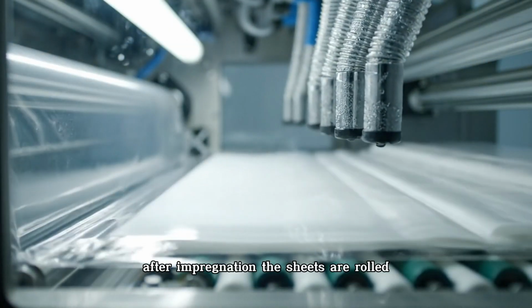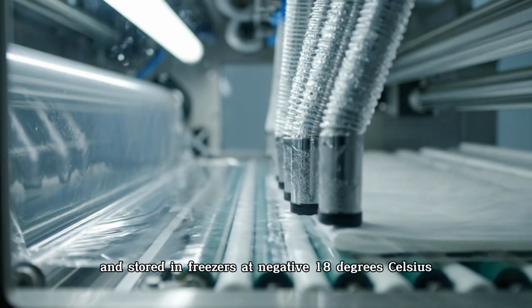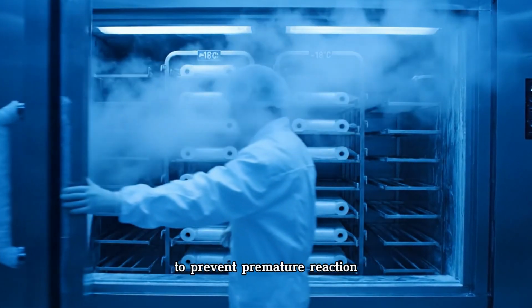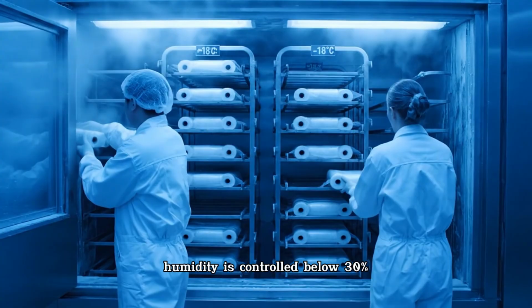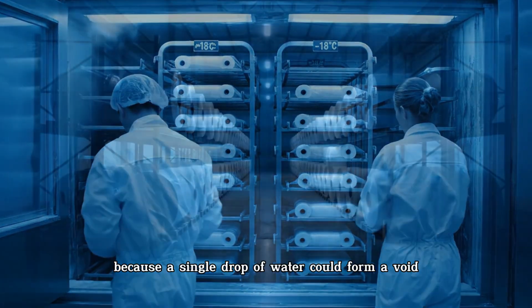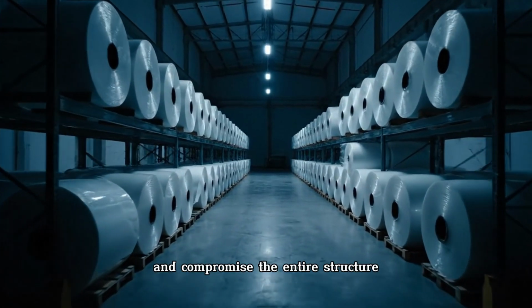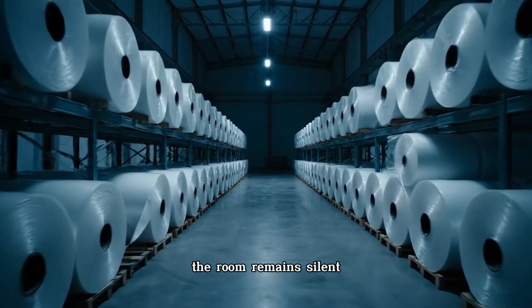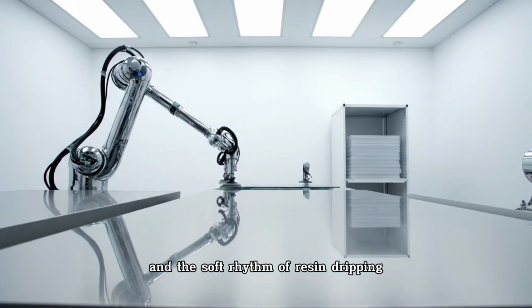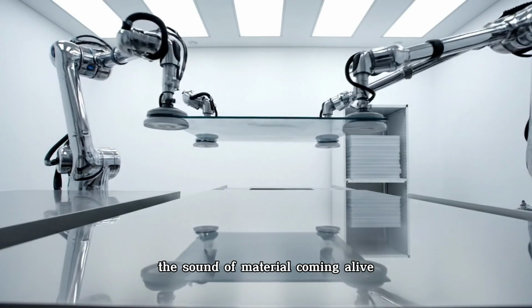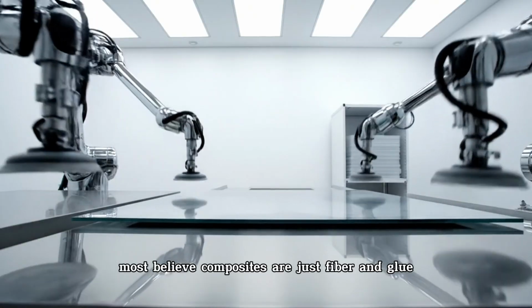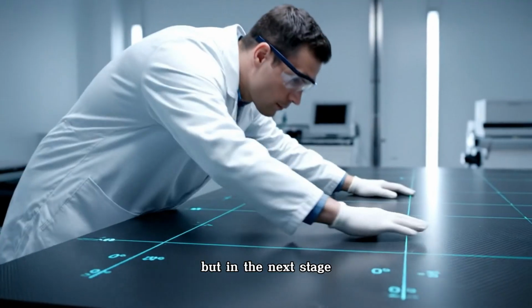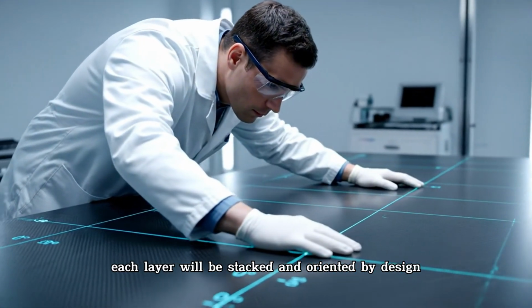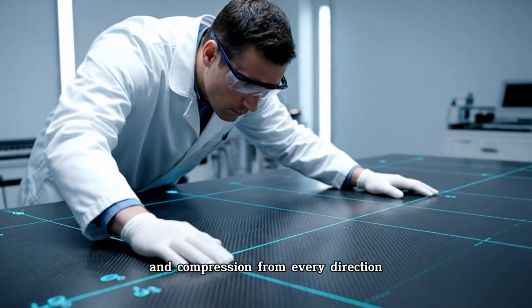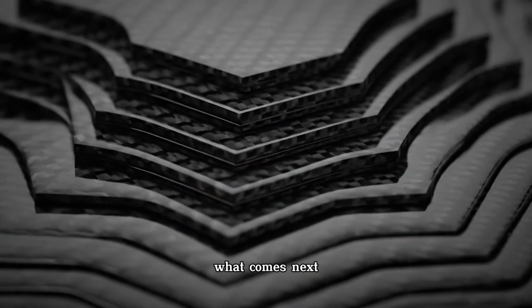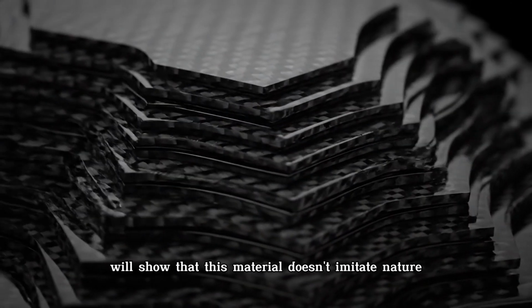After impregnation, the sheets are rolled, sealed in protective film, and stored in freezers at -18 degrees Celsius to prevent premature reaction. Humidity is controlled below 30%, because a single drop of water could form a void and compromise the entire structure. The room remains silent, except for the pulse of vacuum pumps and the soft rhythm of resin dripping, the sound of material coming alive. Most believe composites are just fiber and glue. But in the next stage, each layer will be stacked and oriented by design, creating resistance to torsion and compression from every direction. What comes next will show that this material doesn't imitate nature, it surpasses it.